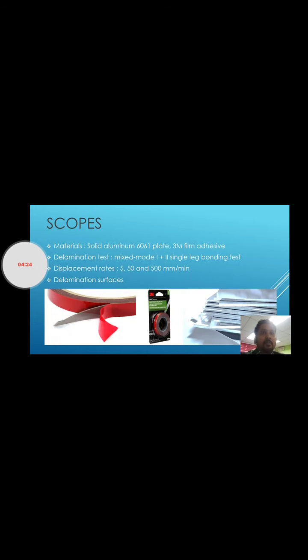Okay, here is the scope. What are the materials that we're going to use to complete this project? Materials: solid aluminium 6061 plate, 3M film adhesive, delamination test mixed mode 1+2 single leg bending test, displacement rates 5, 50 and 500 mm per minute, and of course delamination surfaces.